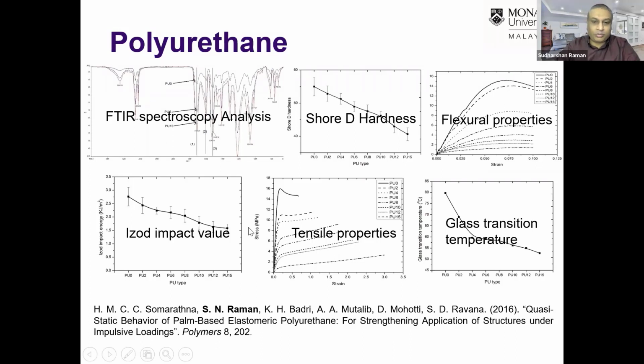What we observed, maybe I will just refer to the tensile graph over here, the bottom middle one. We can see that as the plasticizer content is increased, the elongation capacity of the material increases, but the E value reduces. Okay, but at the same time, the material initially indicated strain softening properties. Later on, they started showing strain hardening properties. Okay, so we wanted something in the middle. We wanted something which has high elongation capacity, at the same time a slightly higher E value.